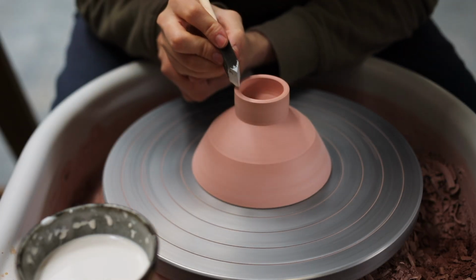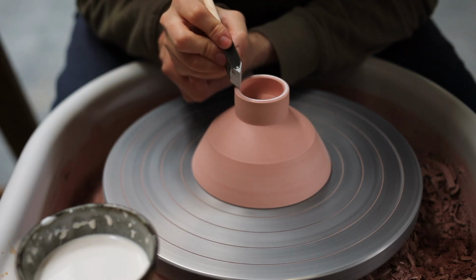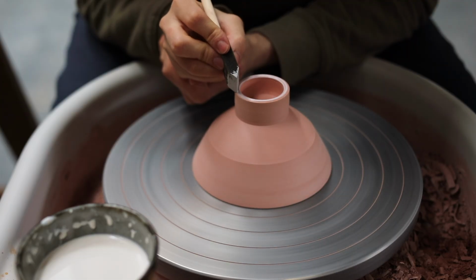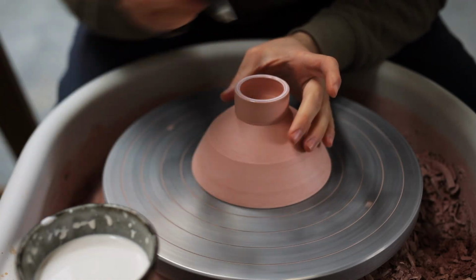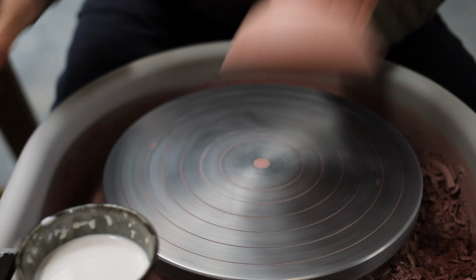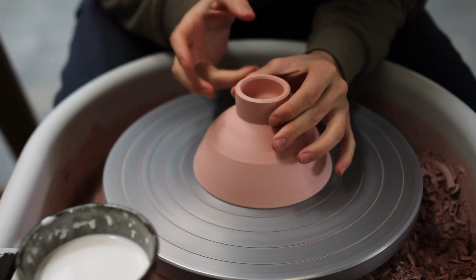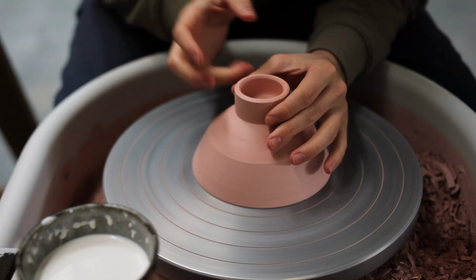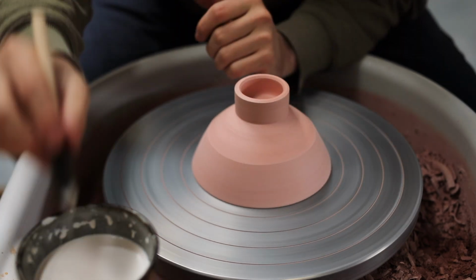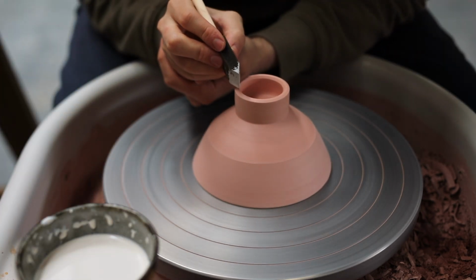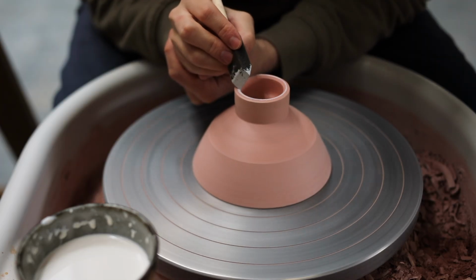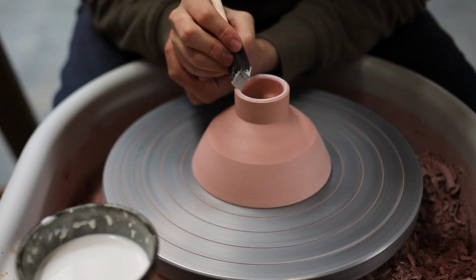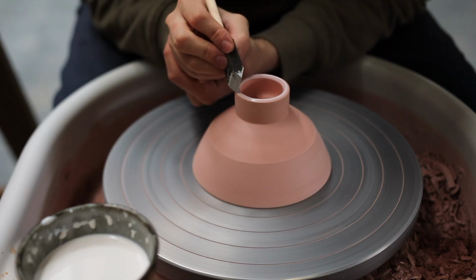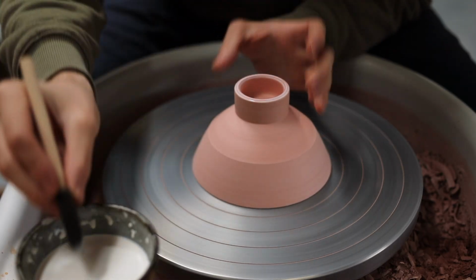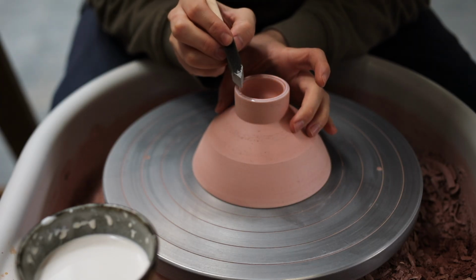Yet, as the clay isn't fully vitrified, it means there are still channels within the body that water can be absorbed into, which is why after each piece has been biscuit fired, I coat the foot in a thin layer of wax. This way the stoneware here won't be able to absorb water, and therefore the raw materials that make up the glaze won't be able to stick to it, which is a good thing, as I don't want glaze coating this very bottom portion of the pot, as it's this part that will make contact with the kiln shelf during the firing, and if it was coated in glaze then it would stick and fuse to it, resulting in the pot having to be cracked off the shelf, a process that will definitely destroy the pot, but it could also damage the kiln shelf itself, which is a far more precious piece of equipment.